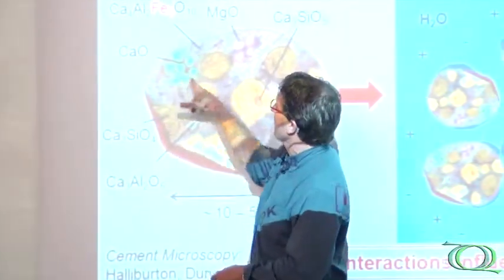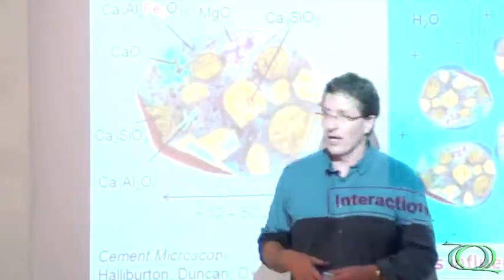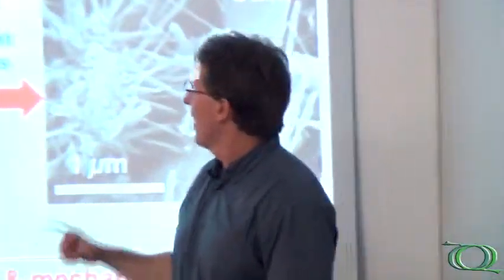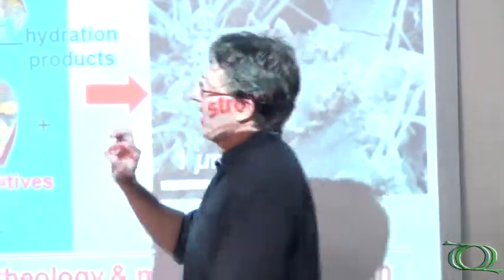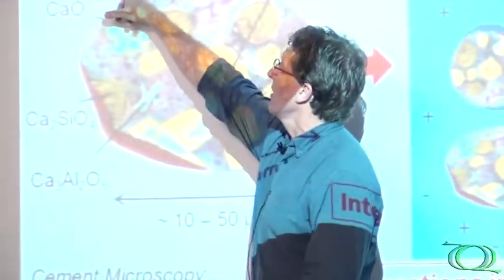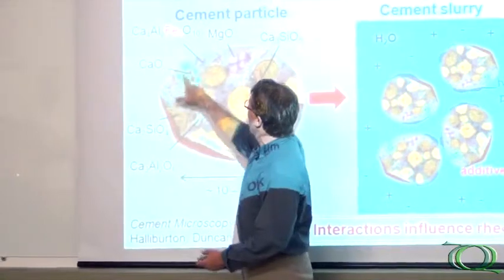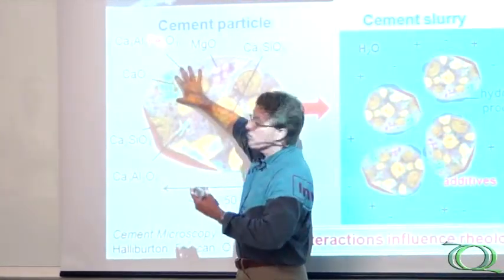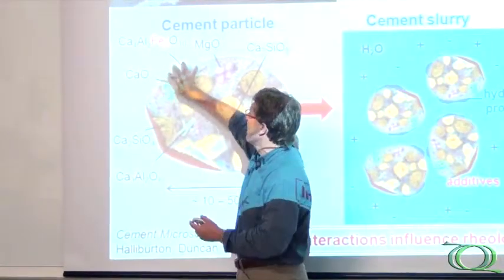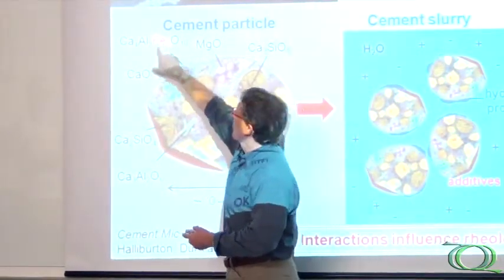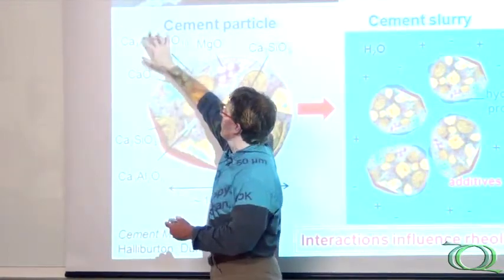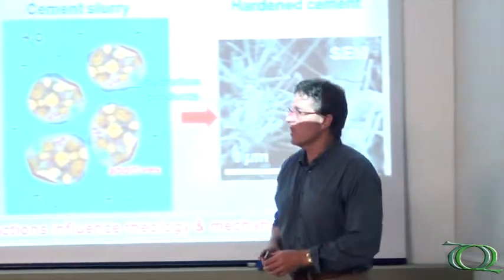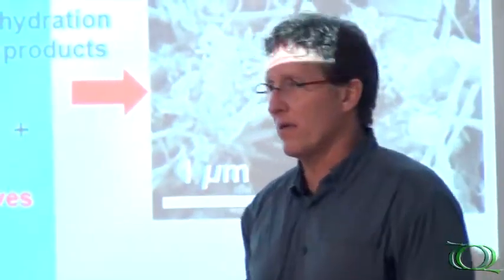But the iron actually contributes broadening because it's paramagnetic. So I'm not sure. That's maybe an expansive question. I don't know what specifically you're asking. But iron is a problem in the sense that it's paramagnetic and makes it difficult to measure these NMR signals because it broadens them. Okay. So iron in any of them is usually troublesome, and so we tend to work with systems where we understand the chemistry with lower iron contents, just to make the signals better resolved and the interpretation more clear.